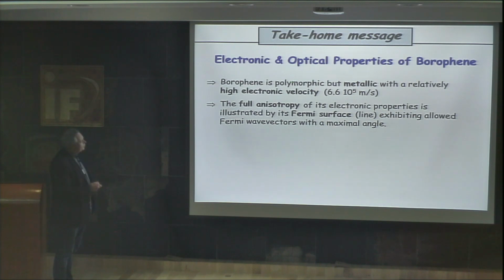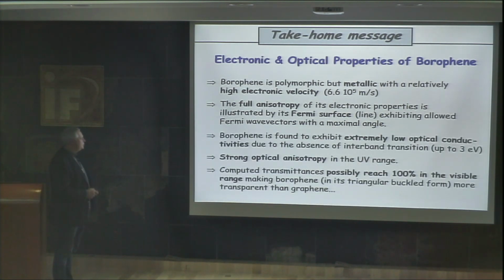Borophene is polymorphic, but mostly metallic with high electronic velocity. The full anisotropy of its electronic properties has been analyzed with the Fermi surface. Borophene is found to exhibit extremely low optical conductivity with the absence of interband transition up to 3 eV. There is a strong optical anisotropy in the UV range, and we have computed transmittance which possibly reaches 100% in the visible range, making Borophene more transparent than graphene.